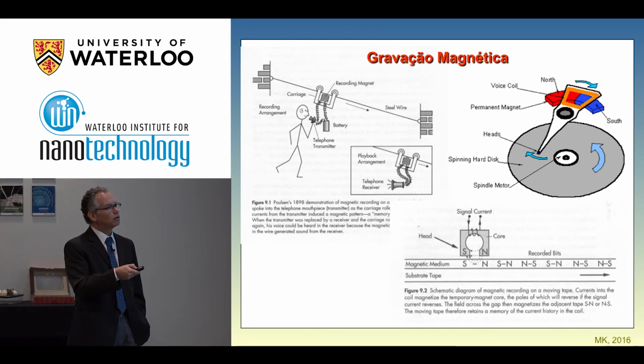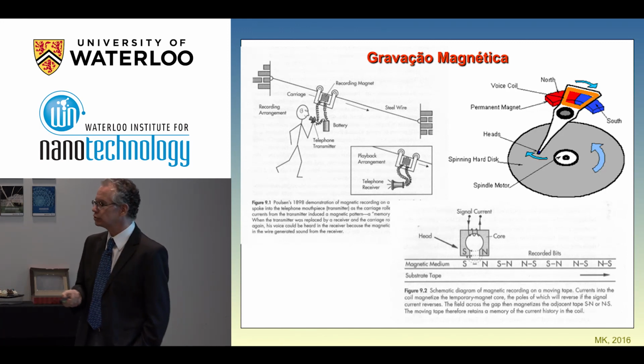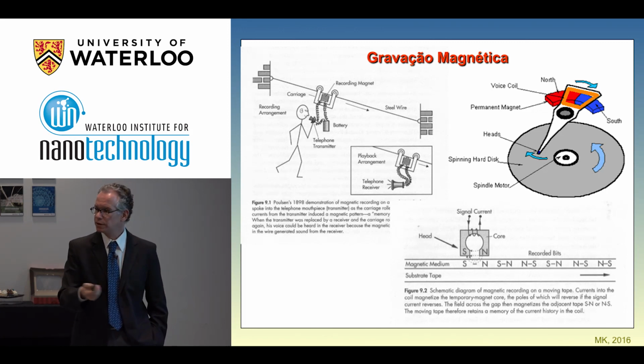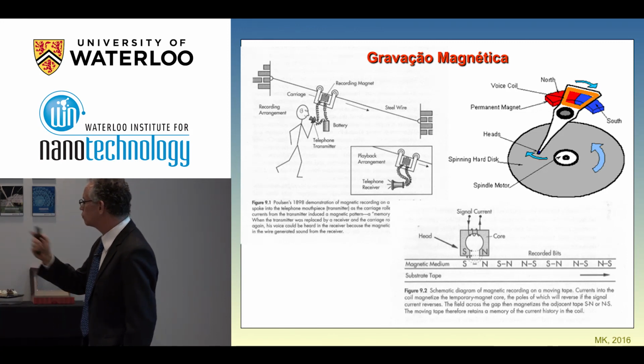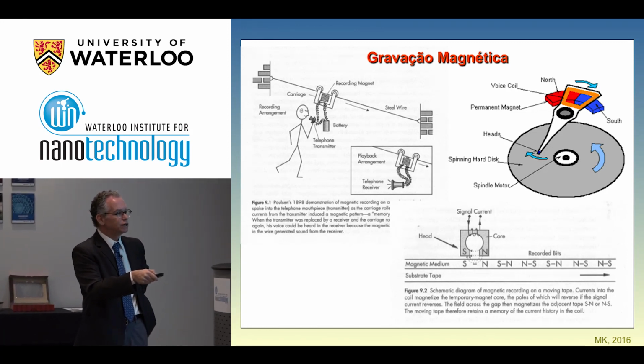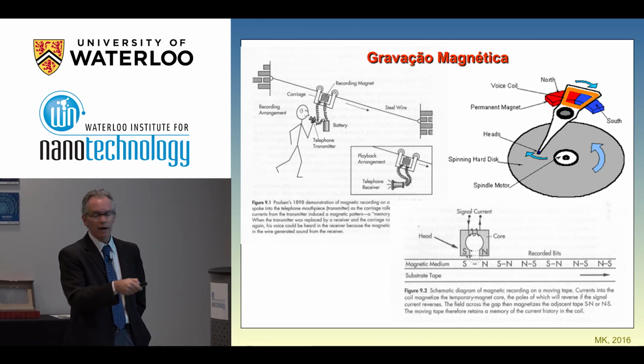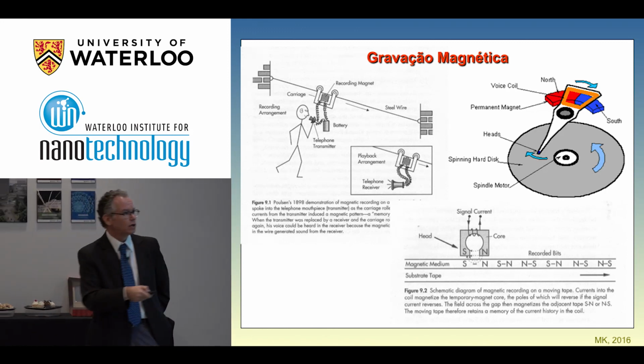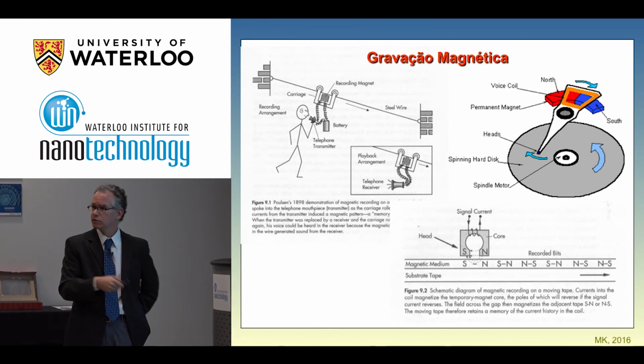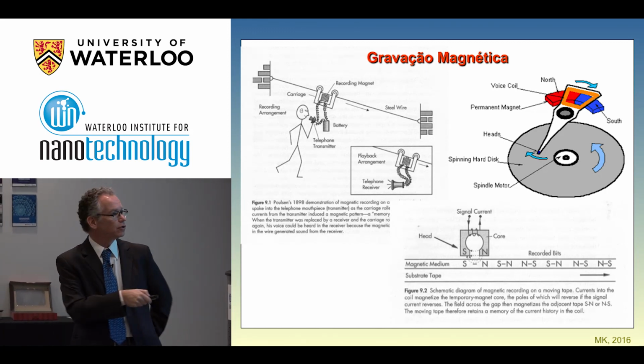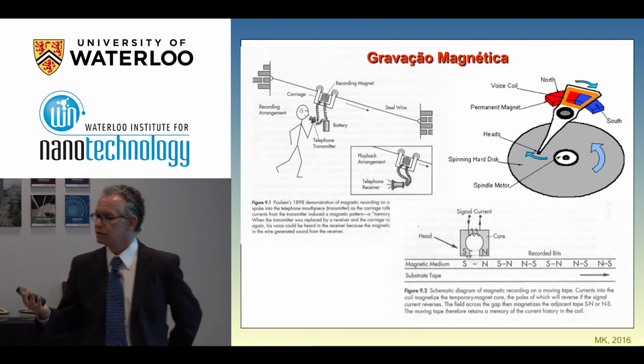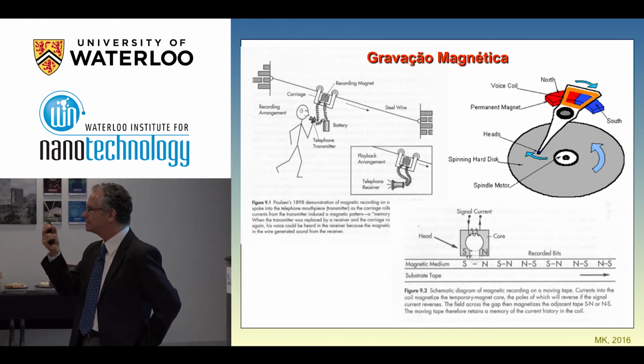And the initial hard disks were essentially the same, with the same concept, the same idea. You have a disk, and the disk has a magnetic medium, and the magnetic medium has regions with magnetization in one direction or the other direction. One direction would be the 1, and the other direction would be 0. Well, you have zeros and ones, and then you have a head, which at the beginning was essentially an electromagnetic device just by induction. You have a magnetic induction here, and you have a signal, and you can say if it's 1 or 0, and you can record.